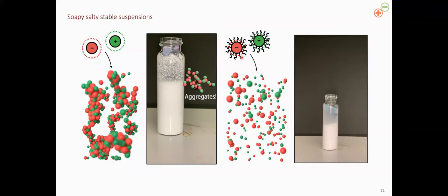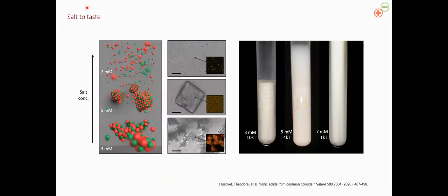And after I shake them up and add them together, we're not going to see any of that aggregation, and this is going to remain stable on the order of days or weeks, okay? So we can actually, with this polymer brush length, we can essentially tuck the electrostatic attraction under the brush and keep those particles from interacting completely. So now it's actually a matter of just tuning the salt concentration just right so we get that electrostatic handshake. And so we should be looking for three behaviors. First is that I don't have enough salt, my interaction range is too long, and all my particles aggregated. So at three millimolar, this is something you'll find. At the other end of the spectrum, we've got too much salt, the electrostatic attraction, the electrostatic interaction has essentially been tucked away under the polymer brush, and the particles are not interacting, it's purely repulsive. And then it remains stable. And finally, somewhere in between, we're going to get an electrostatic bond that can also break. And so then we get reconfiguration crystallization.